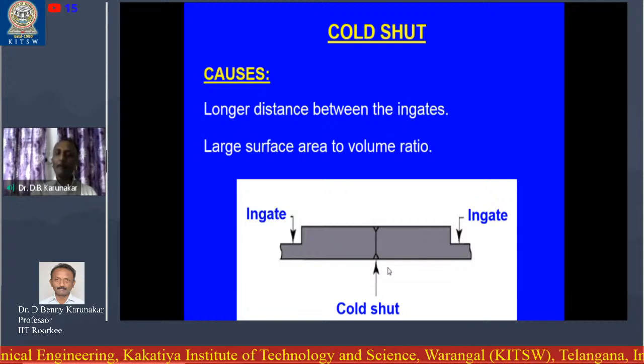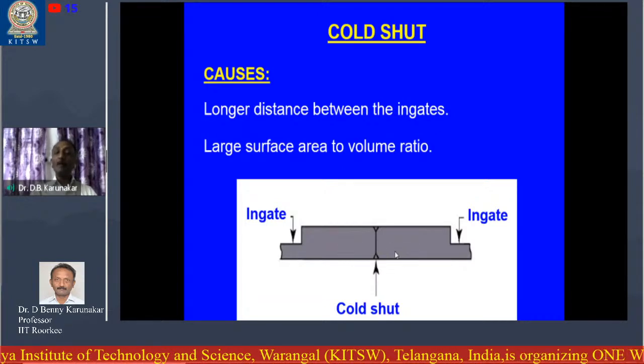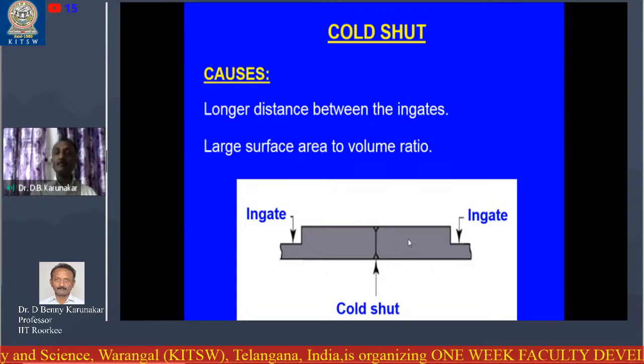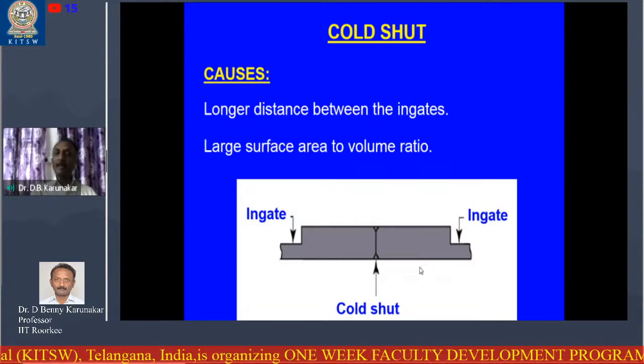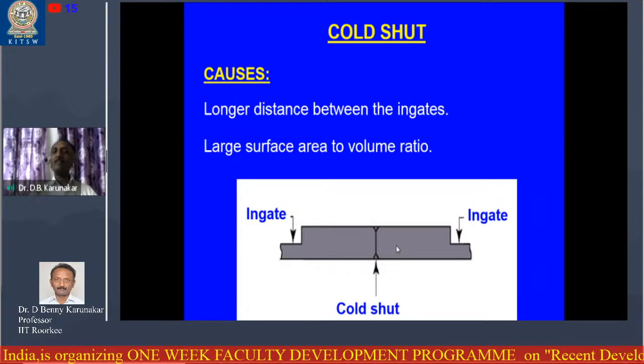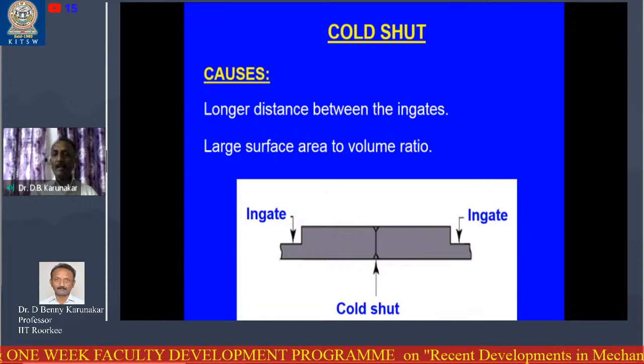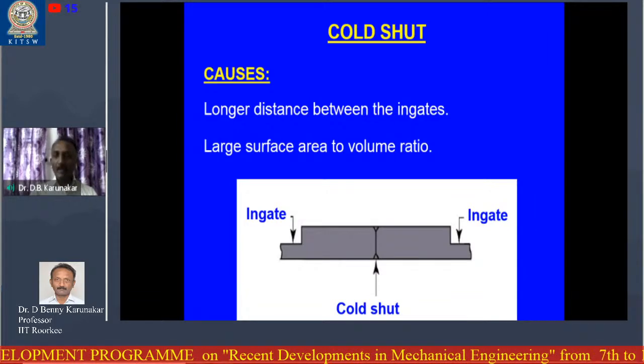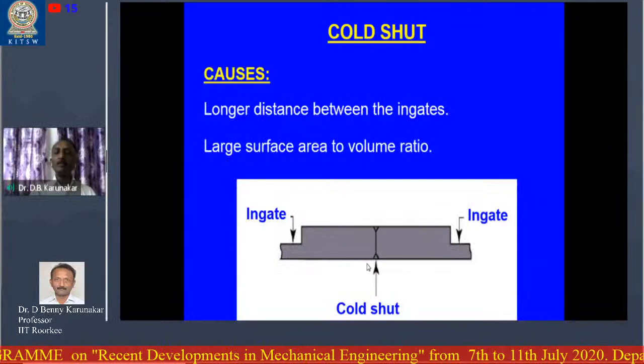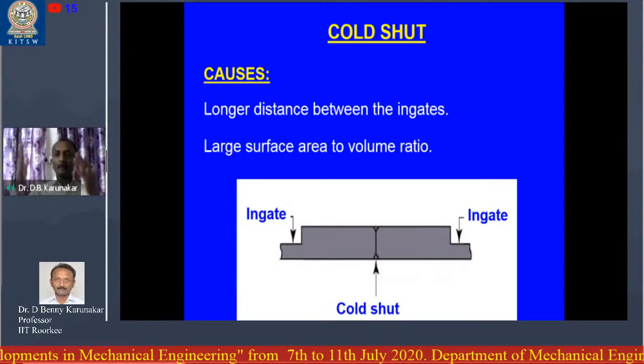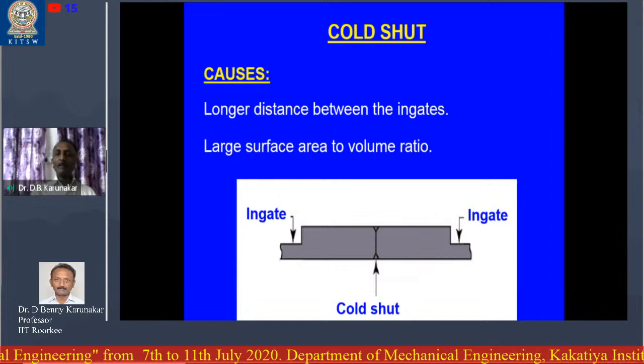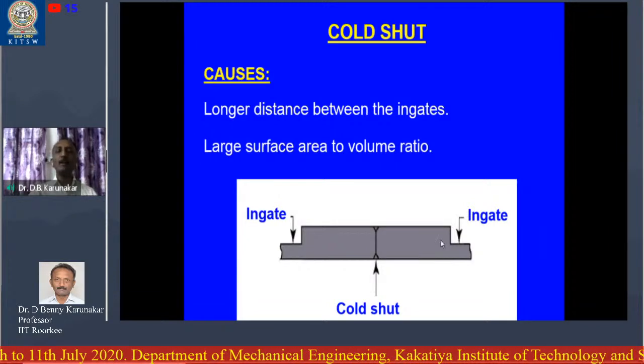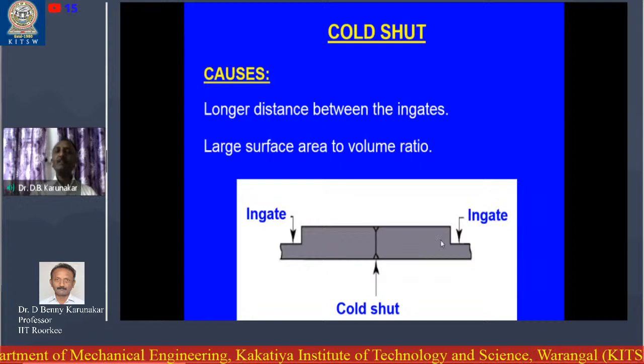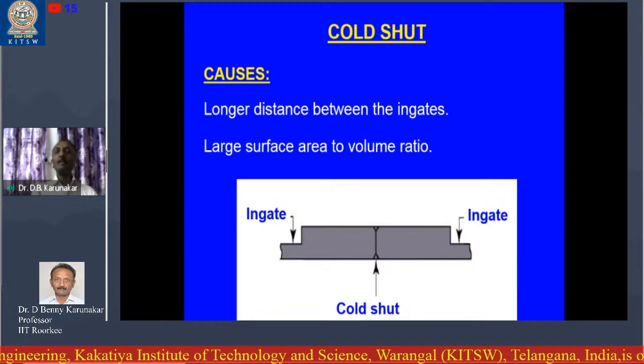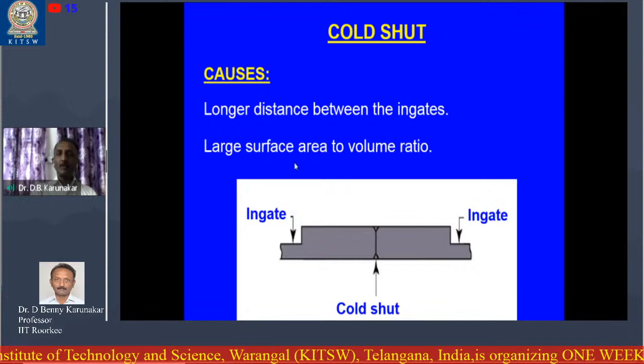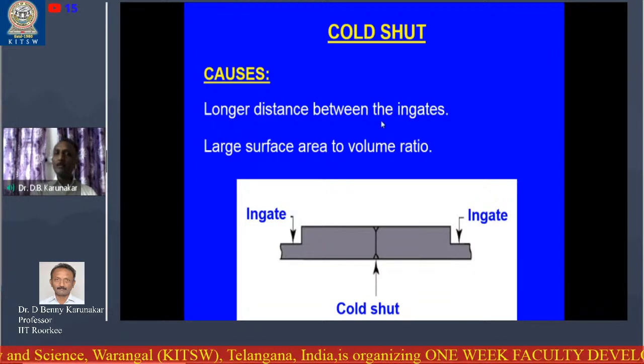Then what will happen? Maybe two streams are coming, and the distance may not be too much - the distance is fair and acceptable. But because the casting's surface area is too much, it has already dissipated heat to the surroundings, and by the time the two streams are coming to the center, they have lost their heat energy, and the fluidity has abruptly come down, and these two streams are not able to mix with each other. So finally there is a discontinuity between these two streams. Large surface contact area is also another reason for the cold shut.